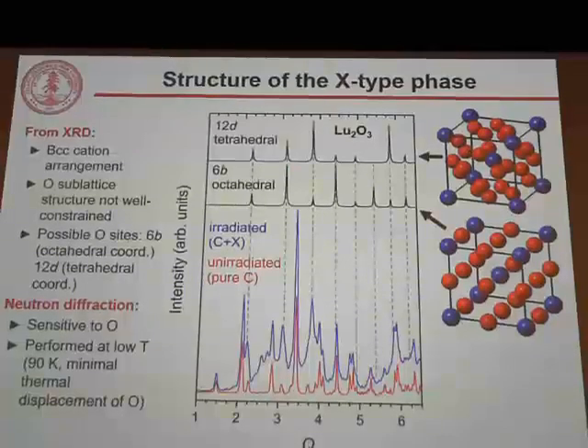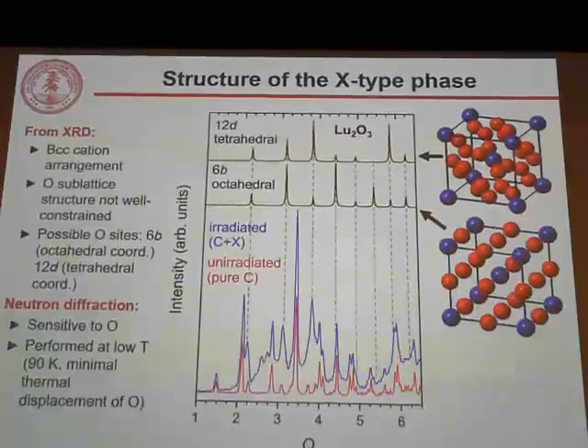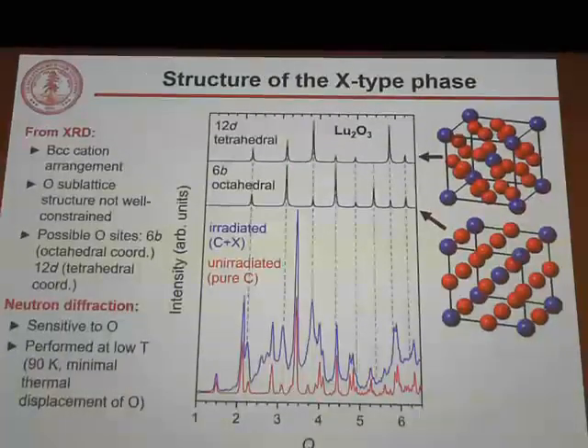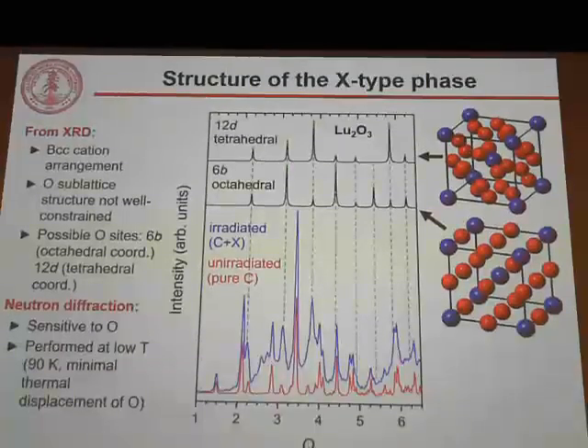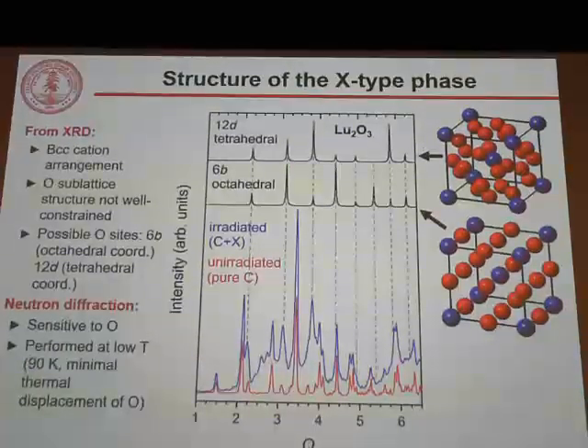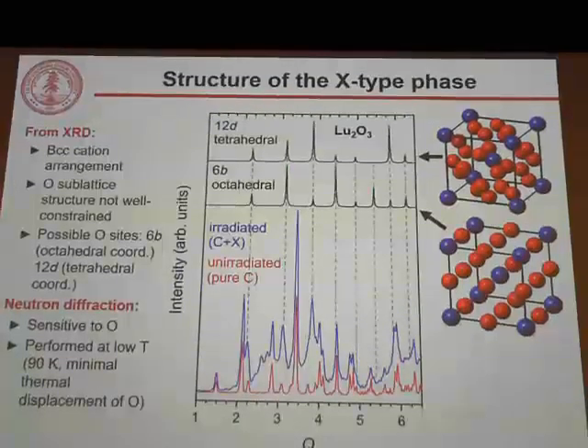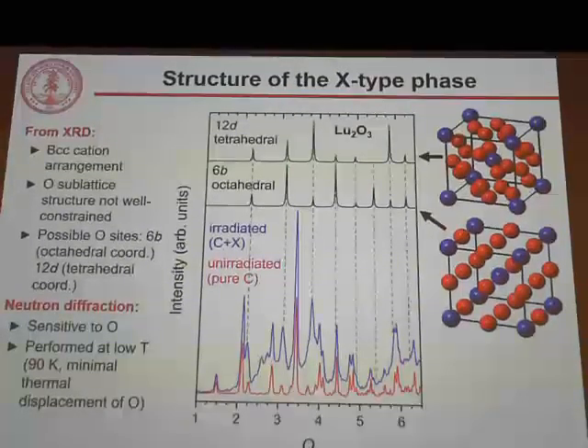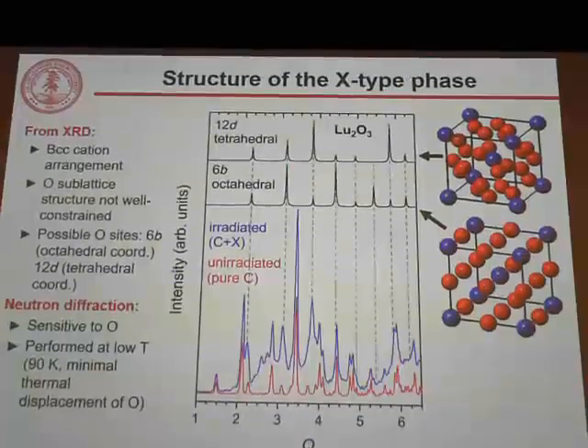So I show those two structures here on the right, on the top the tetrahedral and on the bottom the octahedral. Using neutron diffraction, we can really see the position of oxygen because neutrons scatter strongly from oxygen, unlike X-rays. Also, because we've stabilized this material to ambient conditions, we can perform this diffraction at low temperatures, such that there's minimal thermal displacement. We get relatively nice signal.